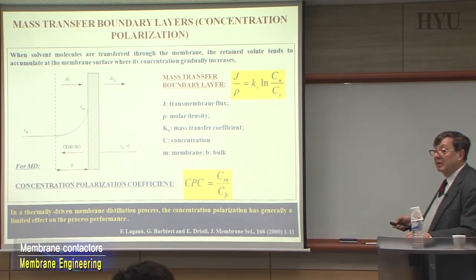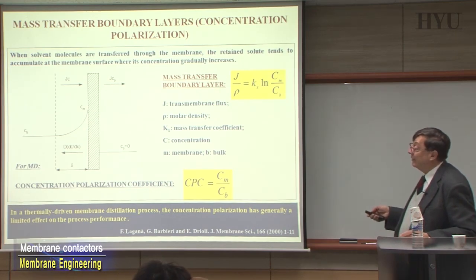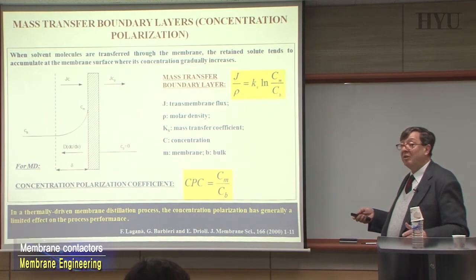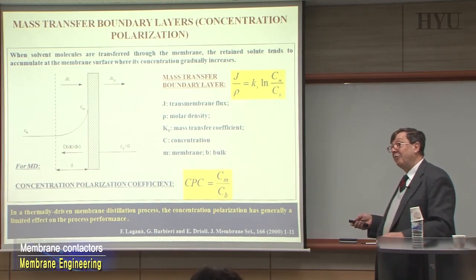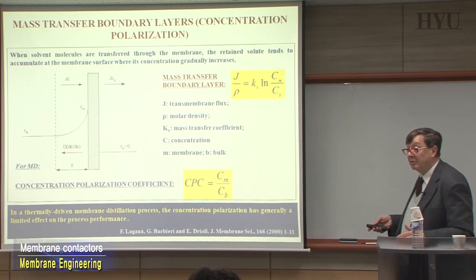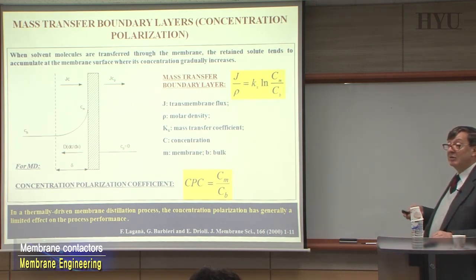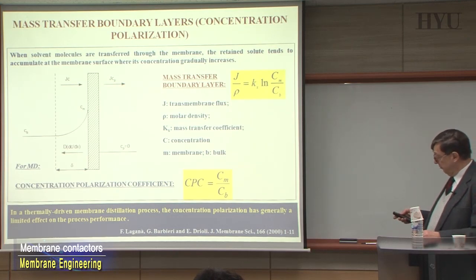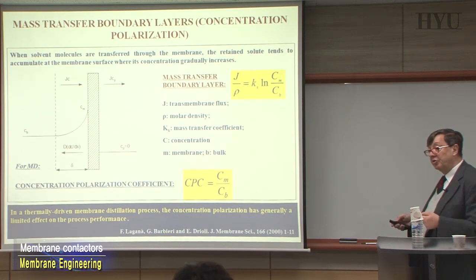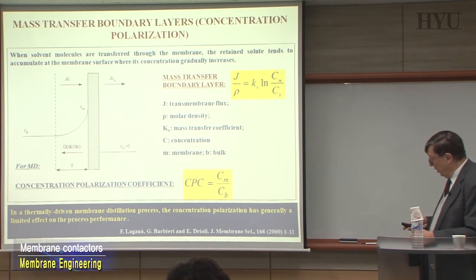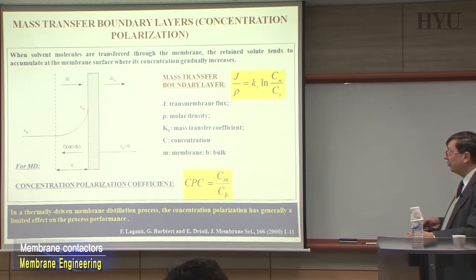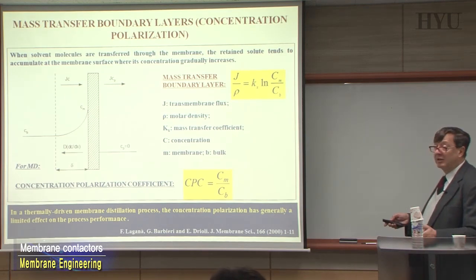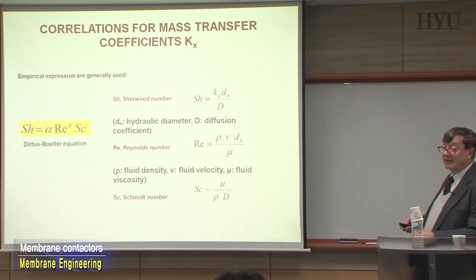And also in membrane distillation, you can create some concentration profile. However, in this case, this change of concentration does not affect too much the driving force in your system. There is no big effect. There is no osmotic pressure that you have to consider here. So this effect is practically negligible, and much more important is eventually the increase of viscosity when you increase the concentration too much. So in first approximation, we are considering that the concentration polarization has a limited effect on the process performance, and that has been very well defined until now.